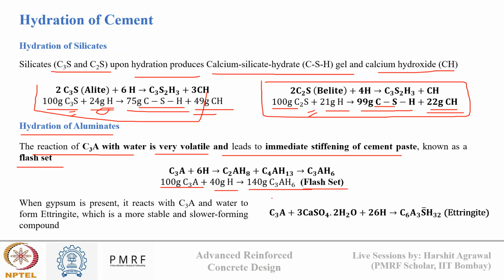Now, we don't want our cement to undergo such a reaction, which makes it stiff as soon as we add water. So, to eliminate this problem of flash setting and to make concrete pumpable or workable for practical application, gypsum is added at the end of clinker production. When gypsum is present, it reacts with C3A and water to form ettringite, which is a more stable and slow-forming compound, and it eliminates this flash setting problem.